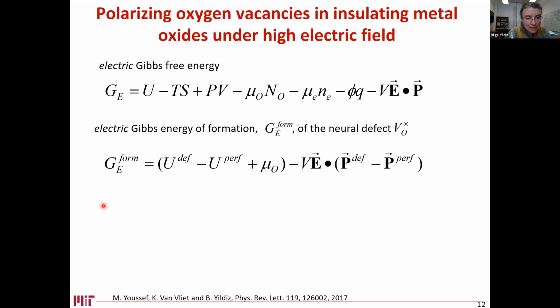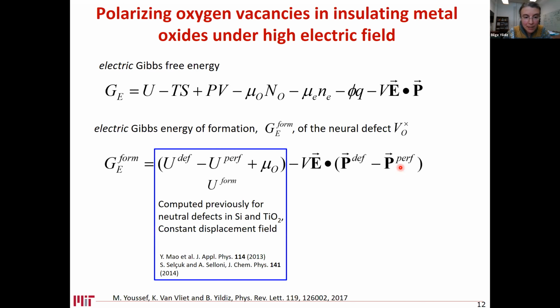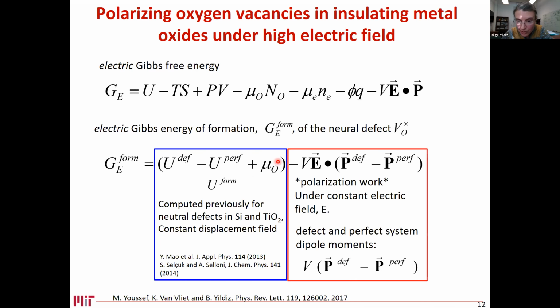So if we then, let's say, calculate the formation energy of a defect that carries charge, for example, an oxygen vacancy that has trapped electrons. So now this is called a neutral oxygen vacancy, but still it has 2 electrons trapped in the site where oxygen doesn't exist. The electric Gibbs energy of formation for this defect includes a term in the end that considers the difference between the polarization of the defective and the defect-free system. Okay, so the internal energy difference under constant displacement field has been addressed in the past before. What we are looking at is this polarization work that is under constant electric field. How does the polarization work affect the stability of different point defects that carry charge in the material?